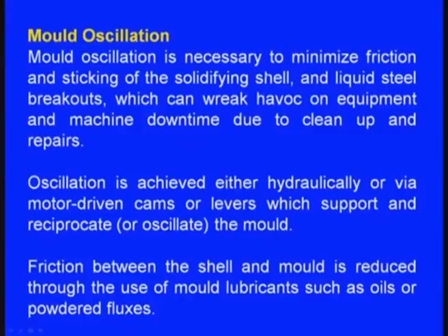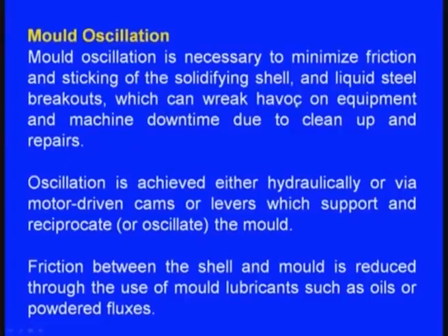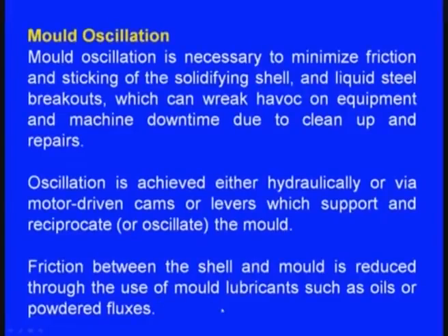Next one, another important term is the mold oscillation. Mold oscillation is necessary to minimize friction and sticking of the solidifying shell and liquid steel breakouts, which can wreak havoc on the equipment, with machine downtime due to cleanup and repairs. Oscillation is achieved either hydraulically or via motor driven cams or levers which support and reciprocate the mold. Friction between the shell and mold is reduced through the use of mold lubricants such as oils or powdered fluxes.